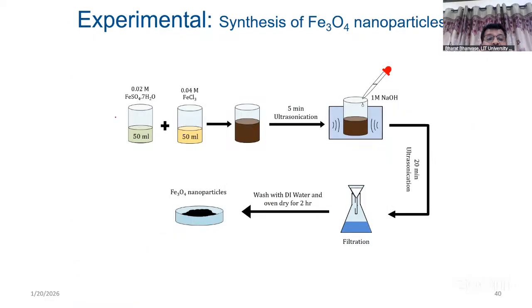So what we did - FeSO4, FeCl3 is added, that mixture was done, and then it was sonicated in a bath sonicator, and addition of NaOH was done. This ultrasonication continued after addition, and after that filtration, which will lead to the formation of Fe3O4 nanoparticles.